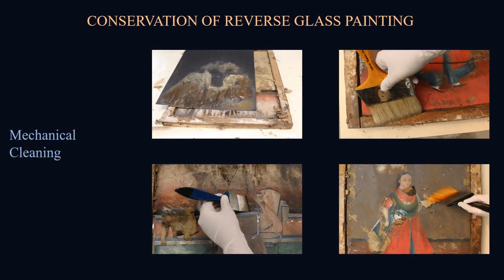Now I would like to talk about conservation of reverse glass painting. The conservation process involved treatment of both the glass support and the paint layer. The first step that was undertaken was antifungal treatment, for which the paintings and their frames were kept under indirect sunlight. After this, mechanical cleaning of both the frames and the paint layer was done using a soft flat brush to remove superficial dust and dirt.